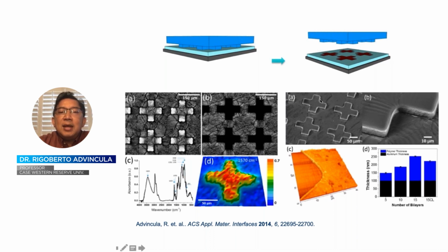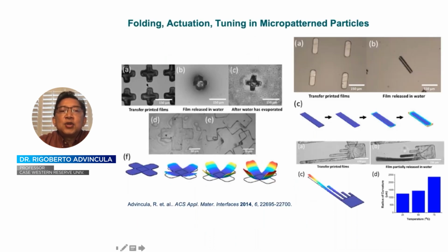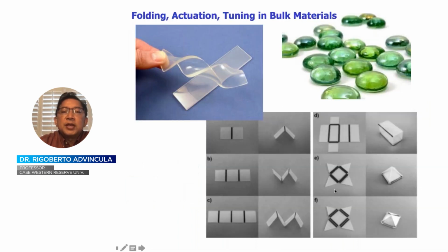And the reason we made this shape is that this cross shape has the ability to fold, so that's your property, by a stimuli afforded by a solvent. So for example, as shown here, those crosses that we form, they start folding the sides and show that we are able to control their stimuli response simply by the environment and exposure of those particles. And we were able to expose them on cylindrical surface as well as tuning fork surfaces.